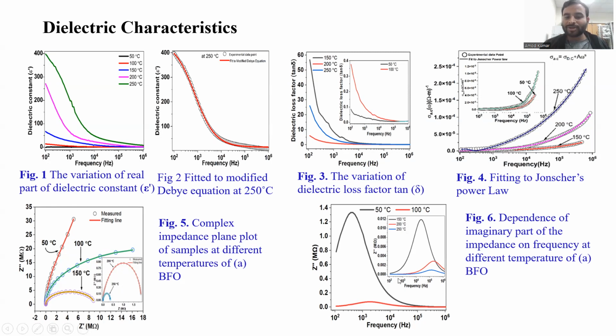One of the figures is between Z double dash and the frequency. We see there are peaks, one and many others. The peaks appear on the left side at lower frequency and also at higher frequency. The lower frequency says one thing, the higher frequency says another. The peak describes the presence of electrical relaxation in the co-doped compound.